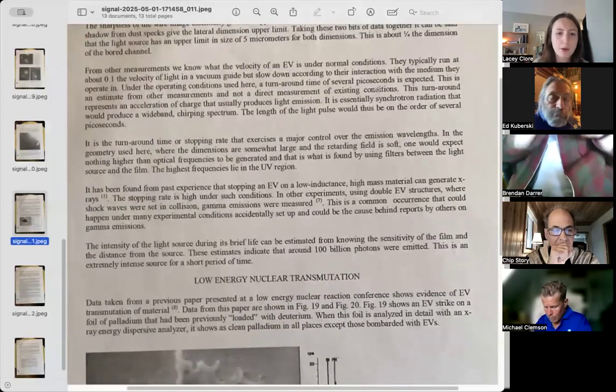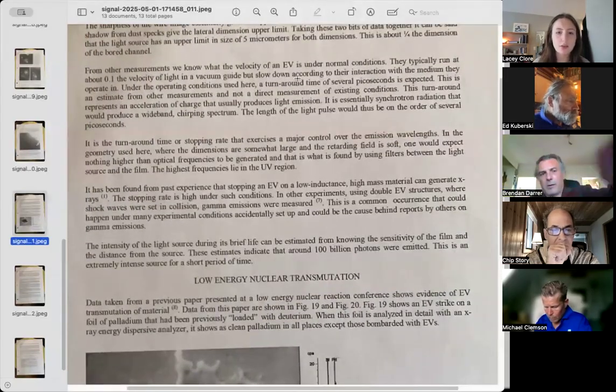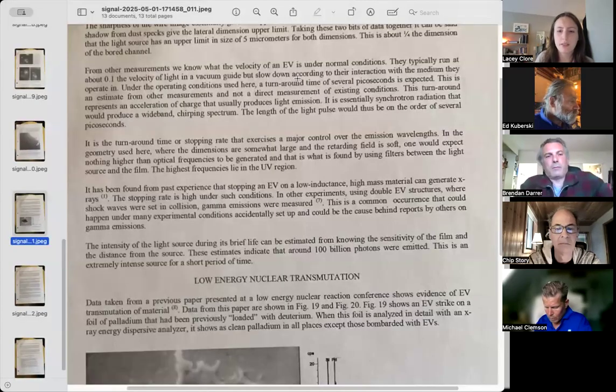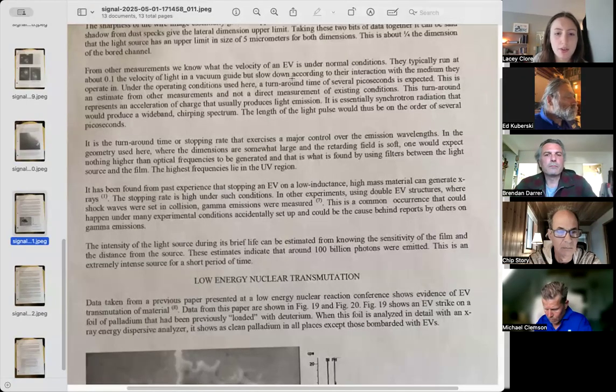From other measurements, we know what the velocity of an EV is under normal conditions. They typically run at about 0.1 the velocity of light in a vacuum guide, but slow down according to their interaction with the medium they operate in. Under the operating conditions used here, a turnaround time of several picoseconds is expected. This is an estimate from other measurements and not a direct measurement of existing conditions.